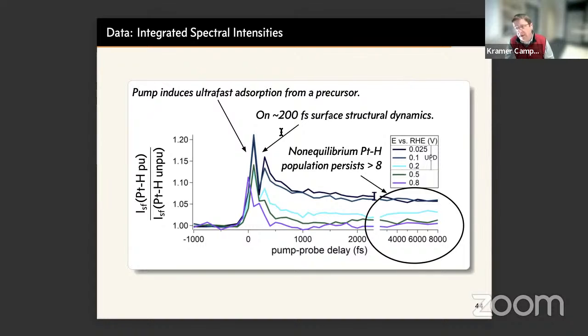Okay, if you do this over the infrared region that I showed before, and you just integrate over all the intensity, you find a signal that looks like this. There are several features that are worth noting. The first is that for ultrafast timescales, one sees an increase in absorption near time 0 that lasts, say, a few hundred femtoseconds at all potentials, right? So within the double layer at 0.8 and 0.5 versus RHE, and also within this UPD region.